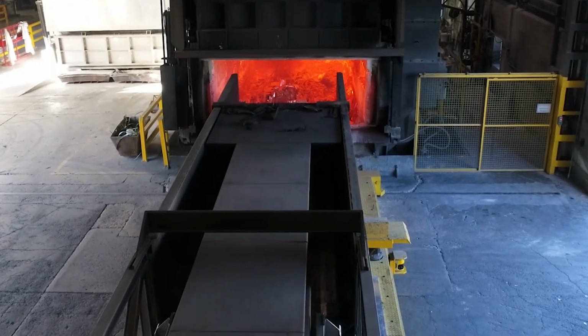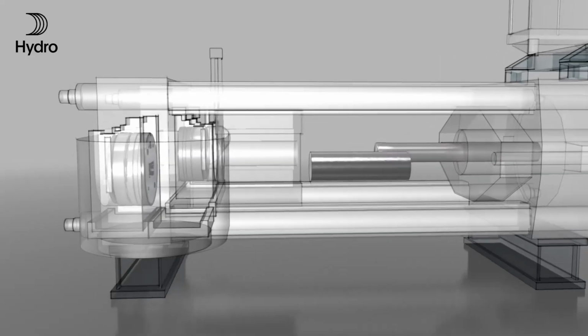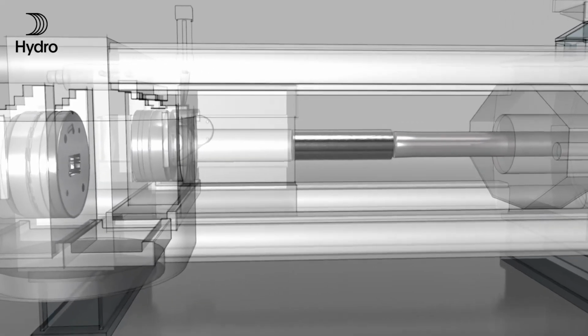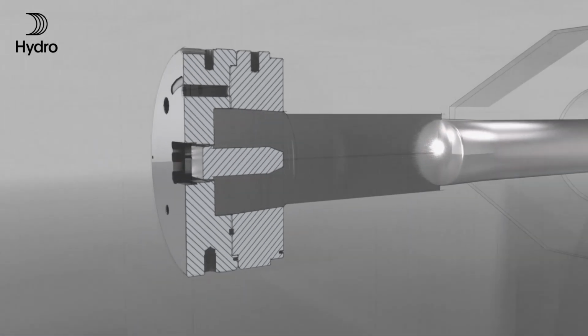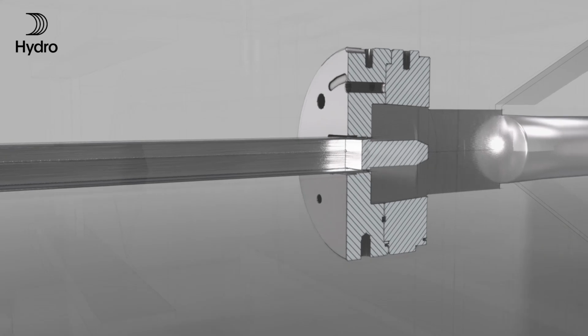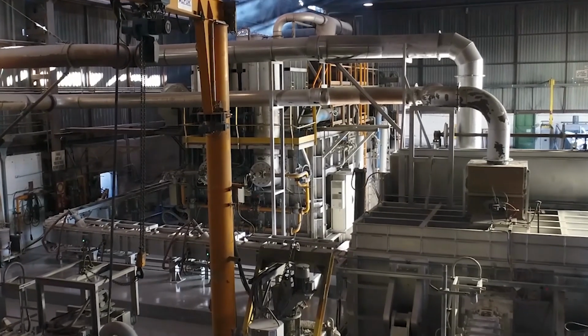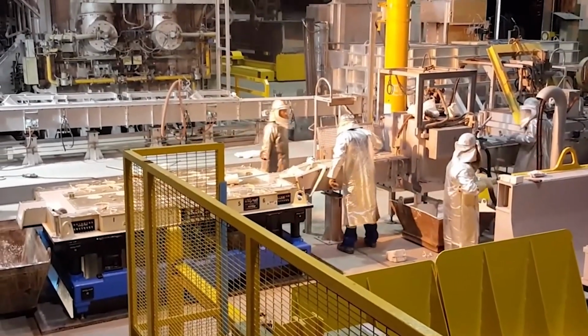If we look more now to the extrusion business, the process itself, we start with an aluminium billet, which is a big block of aluminium that we heat, put that into an extrusion press. And there with huge forces, up to 8,000 tons of pressure on this block, we will push it through an extrusion die, which will create the shape of the profiles. We extrude that over a length of 50 to 60 meters. We cool it down, and immediately after we will stretch it to give it the straightness and the final property.